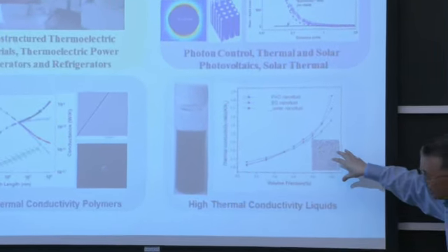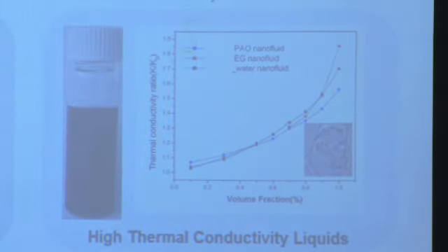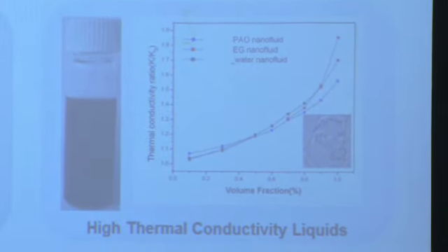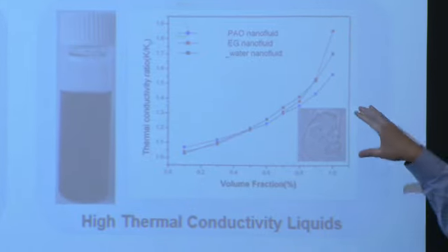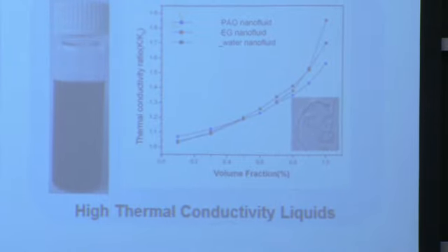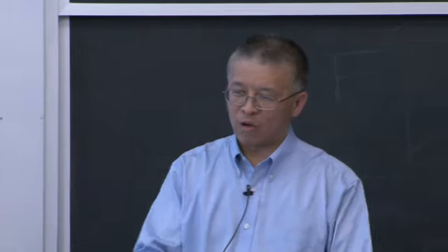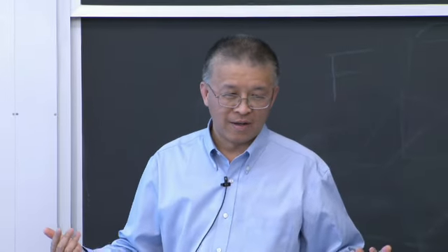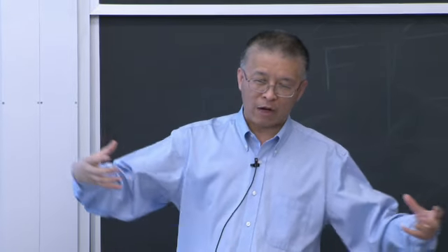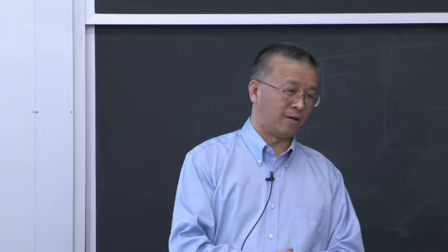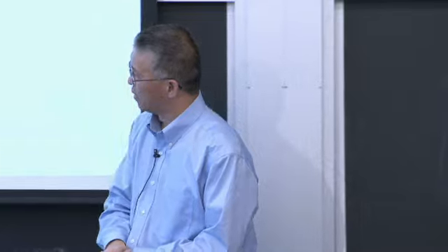In fact, at the end we say, I don't want everything nano. That's where you understand, if you understand physics, not everything is nano, right? So we work on people putting nanoparticles into liquid. Some say it has high thermal conductivity. Others go to the lab, and they say, no, we can't measure it. We struggled for 4 years and eventually figured out that what we need is macro in one direction and nano in the other direction. And that's how we achieve the best thermal conductivity.